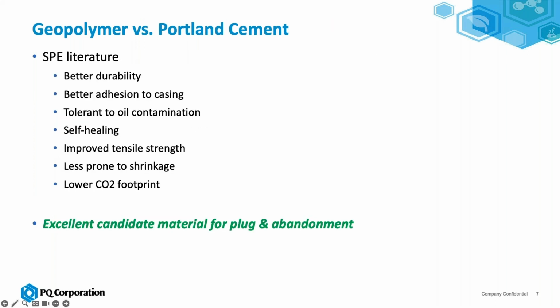Going through the SPE literature, these are the commonly touted benefits of geopolymers versus Portland cement: better durability, better adhesion to casing, tolerant to oil contamination. It has been demonstrated to show self-healing properties, improved tensile strength, so less brittle, less prone to shrinkage, and then a much lower CO2 footprint. So roughly 1/3 the CO2 footprint of Portland cement. Because of these characteristics, they become excellent candidates for plug and abandonment, as well as for remediation applications.